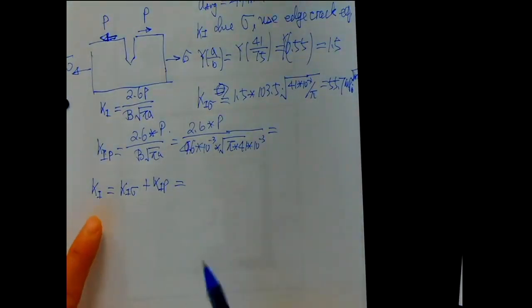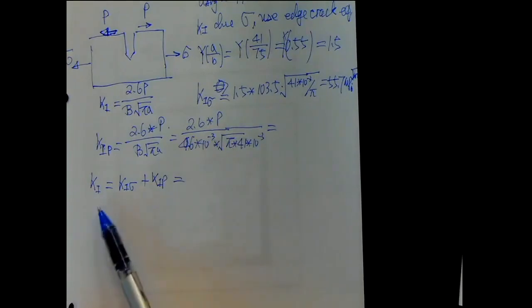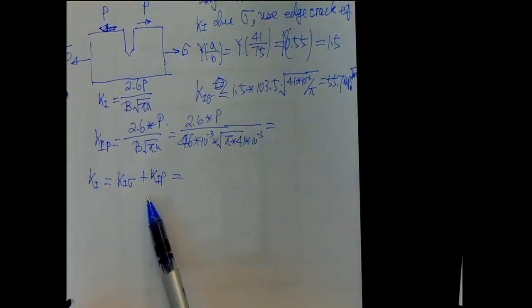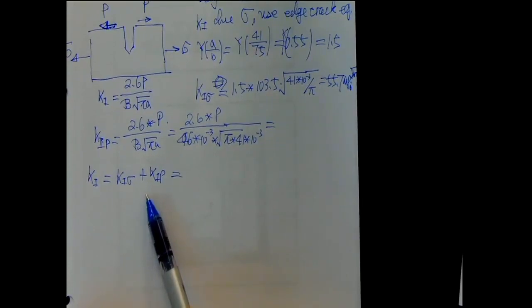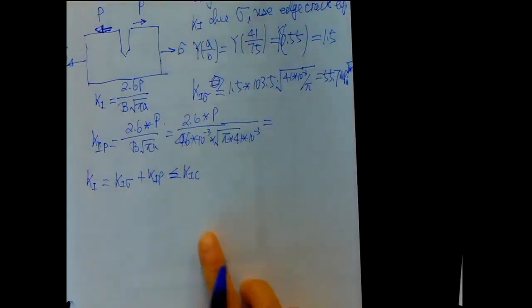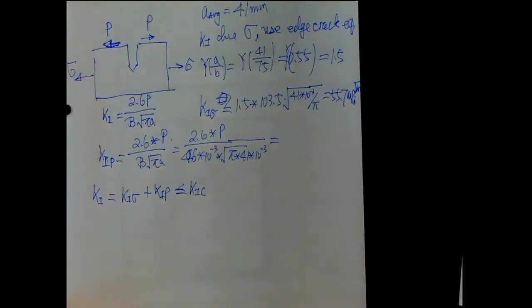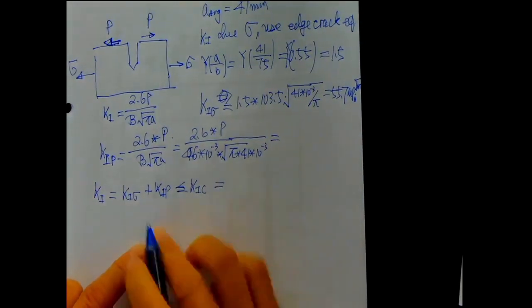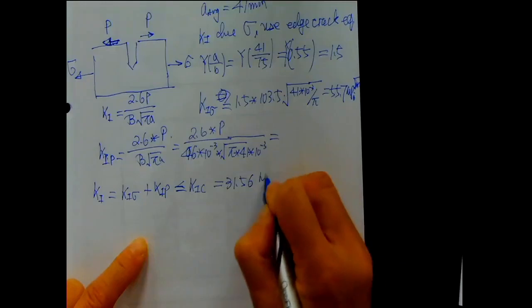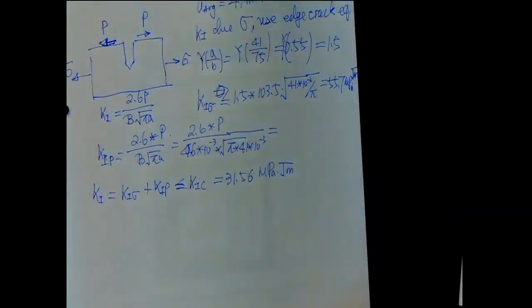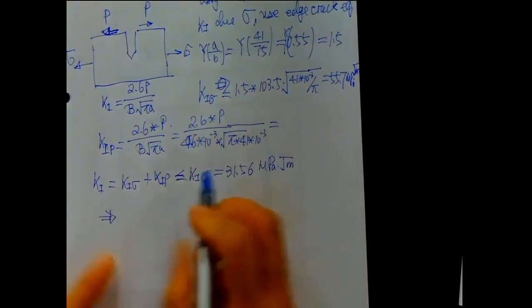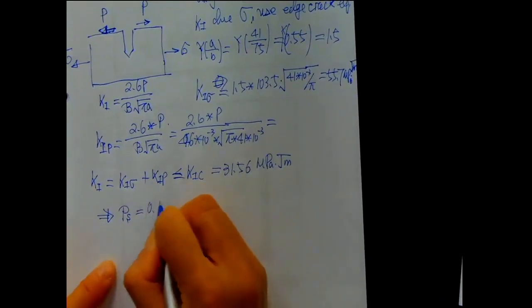So how do I find the P over here? Obviously, right now I don't know P, and what that stress needed to be for the crack to arrest. What's that K1, the stress you need? Should be less than K1C, right? And we already found K1C from the previous analysis. So from here, that is equal to 31.56. And so from that, we could calculate P is equal to, it's actually minus.